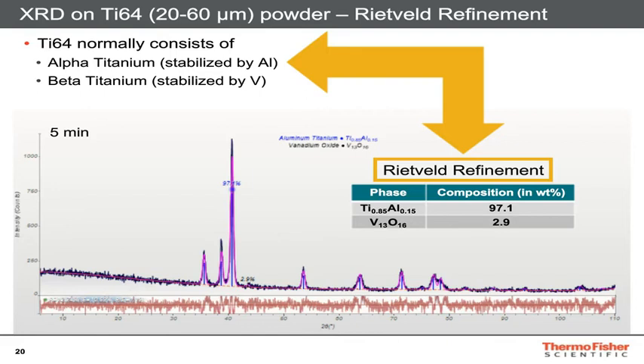And if we now have a look at the diffraction pattern shown on the bottom of this slide, we detect only the alpha phase, but no beta phase, and we can see some vanadium oxide. And by means of a Rietveld refinement, we can also quantify it to some 3% of vanadium oxide. This could be due to oxidation during the melt spraying process or by aging of the powder.